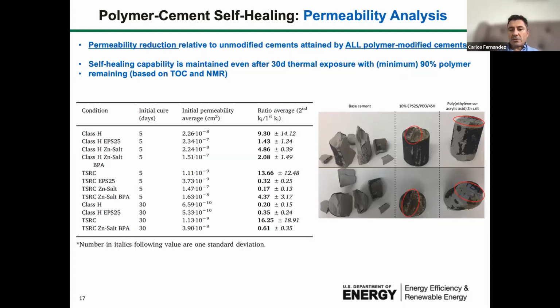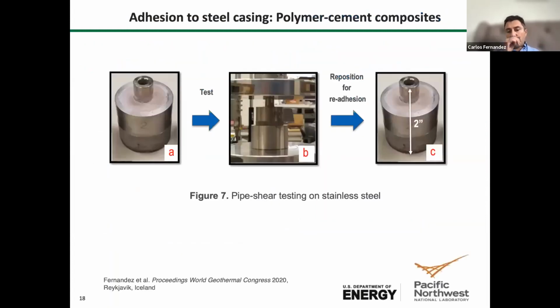We also did some tests for adhesion to casing, and so what the polymer does when it migrates to the surface of the casing. Does it increase the adhesive strength of the material? Does it not? What happens when you actually fail? So you bring this stem down and then break that bond. And when you reset it and wait for the healing event, let's say 5 days at 200 Celsius or at 300 Celsius, does it recover some of this adhesive strength? Does it stay the same?